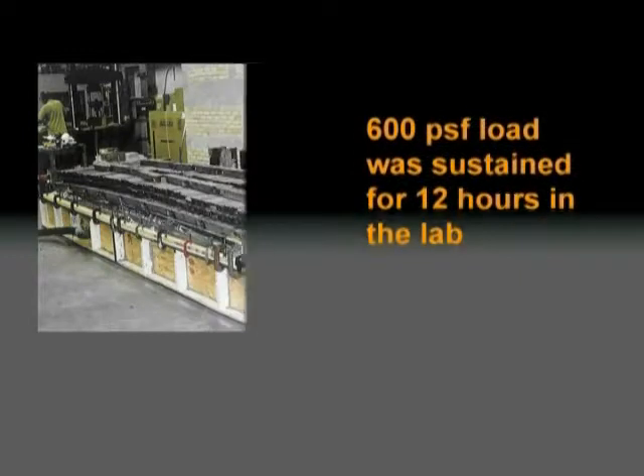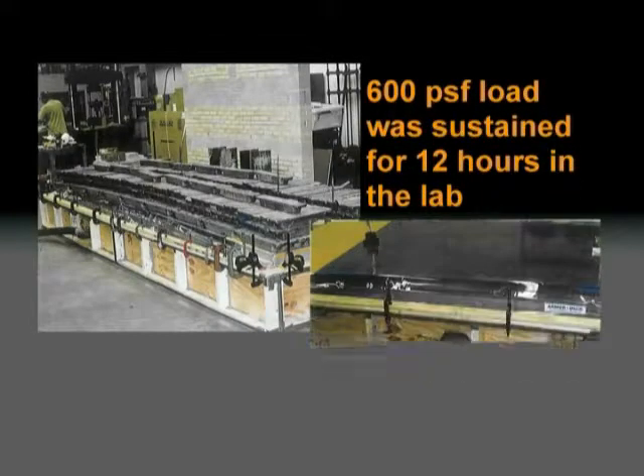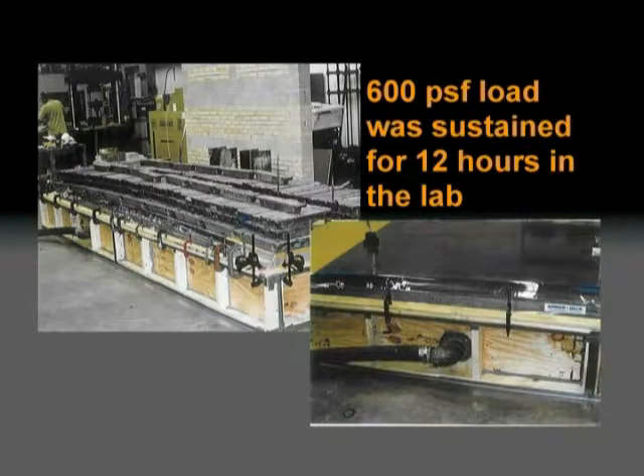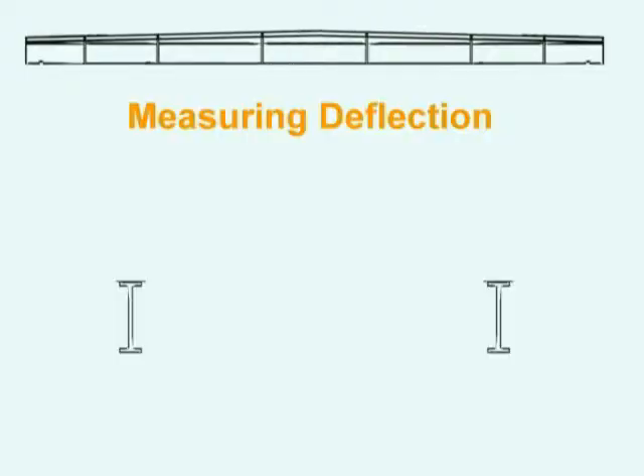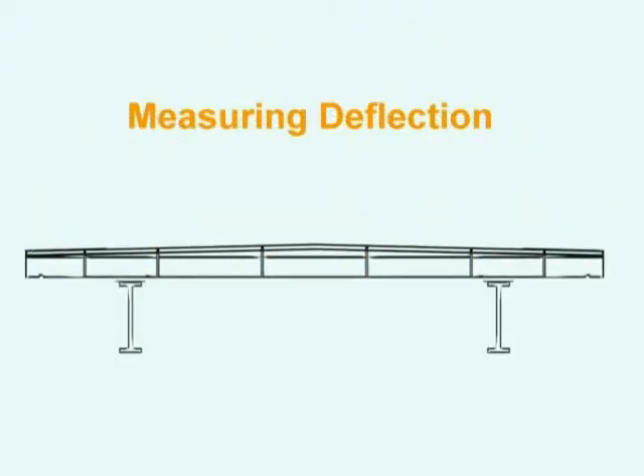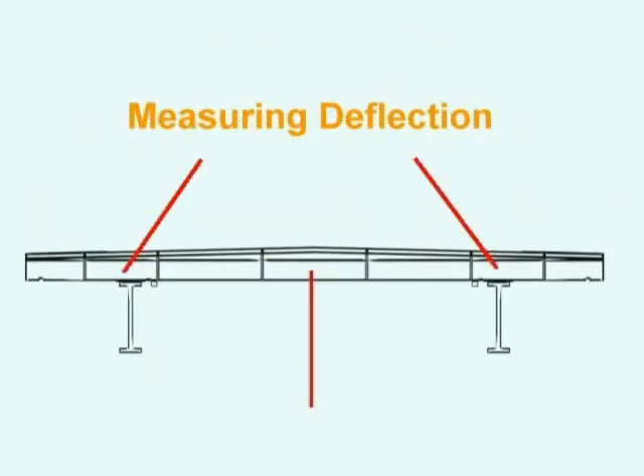It was a combination of the lead weights and the vacuum chamber that we were able to achieve that 600 PSF load, and we held that for 12 hours. During the course of the entire test, we were measuring the deflection at the mid-span and at the support points and at the overhang points on the panel.